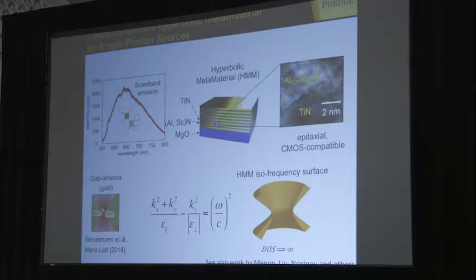Why is it important? Because if you look at the isofrequency surface in k-space, normally it's a sphere if your material is homogeneous and isotropic, or spheroid if it's anisotropic material. But if one of the epsilon is negative, like in this case, in transverse direction, actually two are negative, one is positive, then it becomes hyperbolic. And that's why these materials are called hyperbolic. Why is it important? Because as opposed to sphere or spheroid, where you have a closed surface, and therefore the largest accessible wave vector is limited, here it's an open surface. You have access to very large k's. And also it means that if you calculate the density of states, which is basically the volume between these two isofrequency surfaces, it's divergent. It could be arbitrarily large.